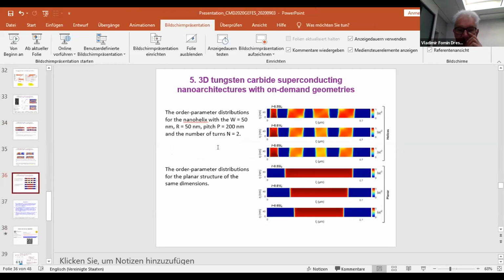I think this will be practically my last slide, which shows that there is a significant difference between the structure of phase slips in a planar structure, these are 3 lower panels, and in a nanohelix, where this interplay between the confinement of screening currents and creation of vortices is dominant.